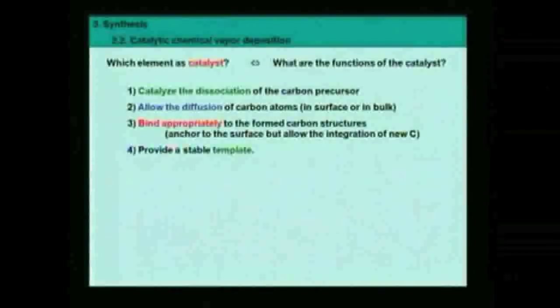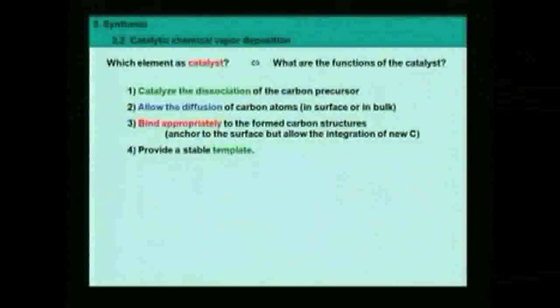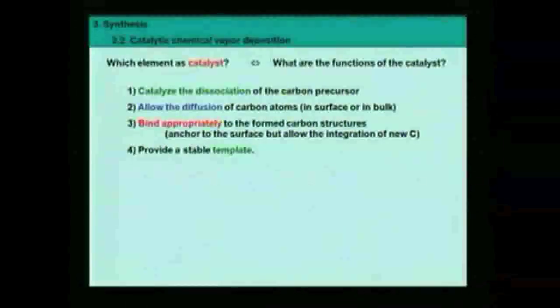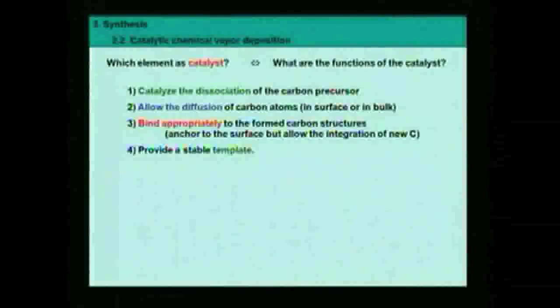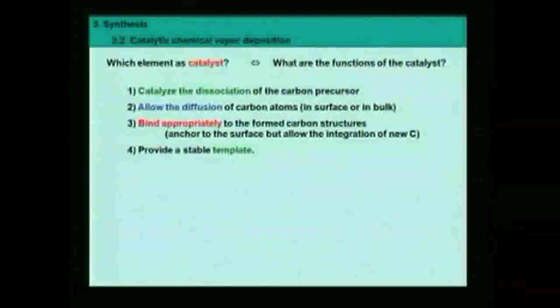And then we also talked about the template effect, which is very important to decide if we will make a flat structure like graphene or a tubular structure like nanotubes. So here we need a template, we need a special shape, and we need this shape to remain during the growth. Remember that we are at very high temperatures, like 600, 700, 1000 degrees C. At this temperature, atoms move very fast. The mobility is very high. So you should not take for granted that the particle remains similar to what it was at room temperature. But despite these problems, we need to keep this stable at least for the duration of the growth.